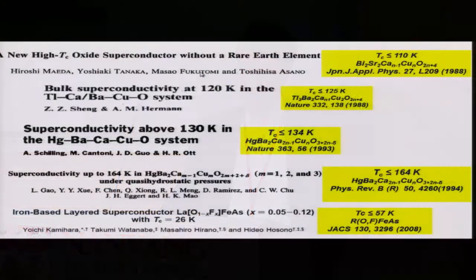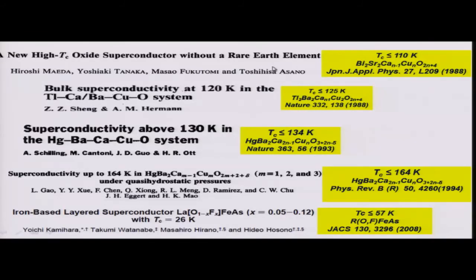So following that, there were some other developments following a similar path, and then a bismuth-based high-temperature superconducting material system was discovered in 1988 with a TC up to 110 degrees Kelvin. Then very quickly, in the United States, Sheng Zhengzhi and A. Hermann found a thallium-based material with TC 125K, and then later on in Zurich, Ott and co-workers found a mercury-based material with TC up to 134 degrees. Then by the application of pressure, we raised the transition temperature up to 164 degrees, which was the record until very recently for superconductors. And later on, I was looking at that, thinking.